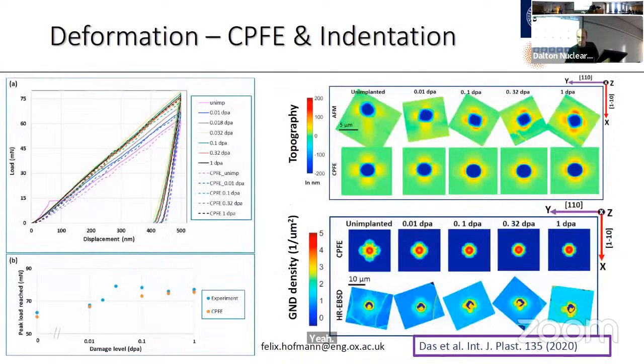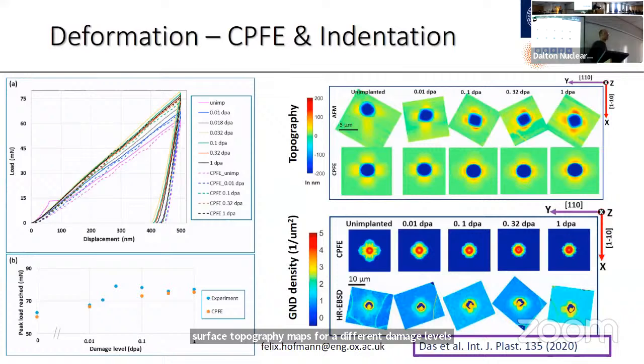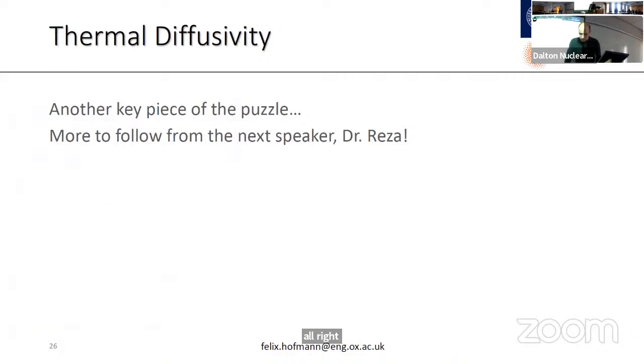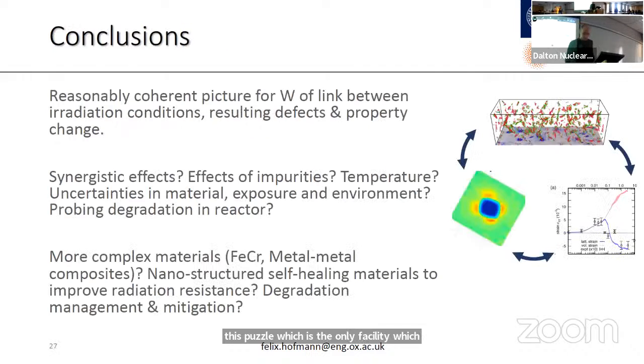And then we also did some crystal plasticity modeling on this, actually adapting the helium-based model. Here are surface topography maps for different damage levels, all in 001 crystals. And then down here is the crystal plasticity prediction, and it matches reasonably well. What I've not talked about at all is this large missing bit of the puzzle, which is the thermal diffusivity, which Abdallah is going to talk about. So I didn't want to steal his thunder. And let me just quickly wrap up.